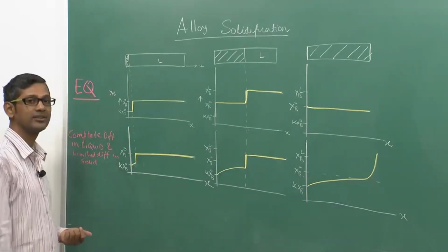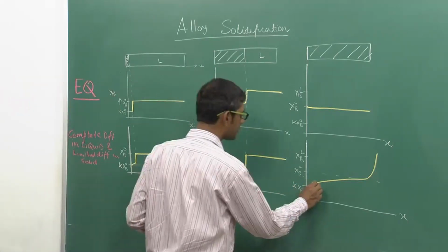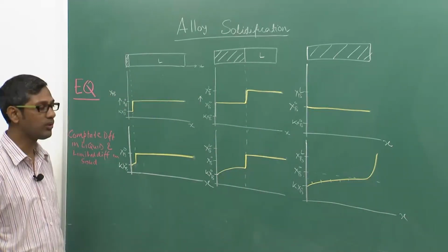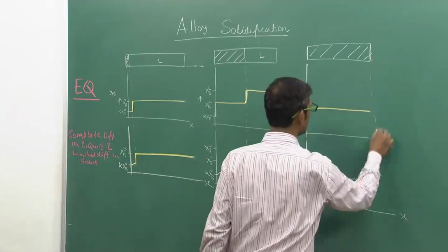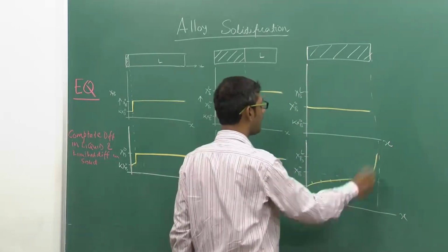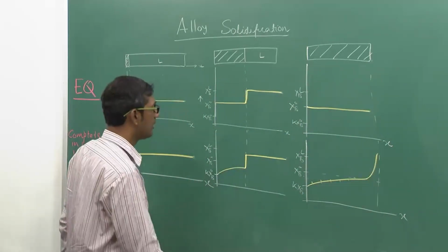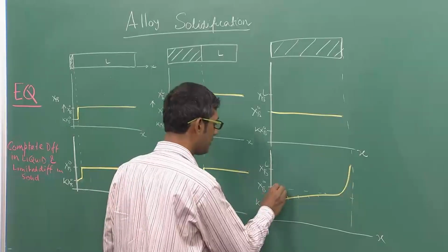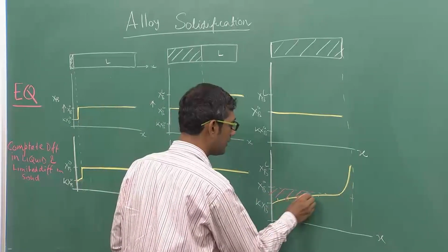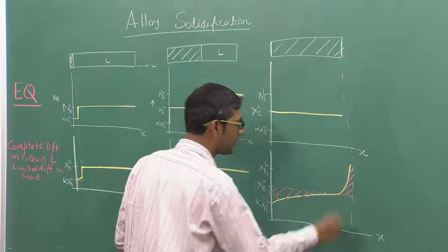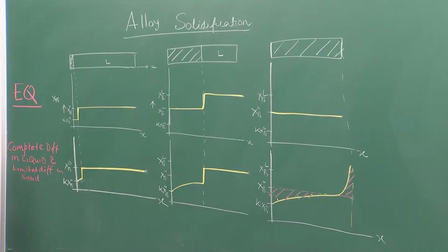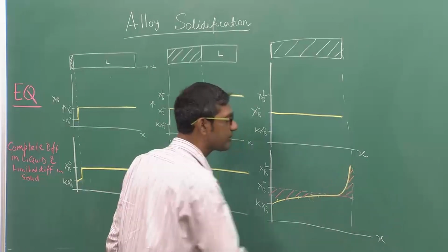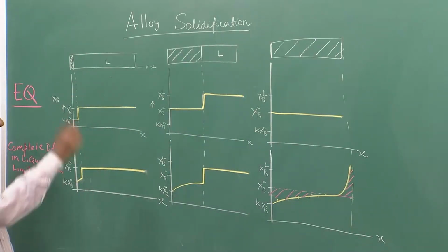It is very clear, solid will have different compositions as a function of positions, you see here, and finally it reaches Xp0 at a later part of these, you can see here, and its composition shoots up, because see the area under this curve, whatever is lost here, solute in the solid, must be same as whatever is the area under this curve, okay, because we cannot destroy solute, okay, that is what it is. So therefore there will be huge composition spike at the end of the sample.